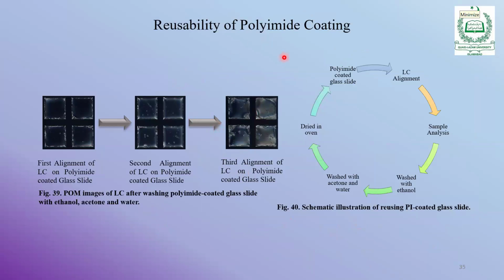Then there is the reusability of the polyimide coating. So first, alignment of liquid crystal on the polyimide coated glass slide, and the liquid crystal aligned. Then sample analysis was done. After the sample analysis, we washed this grid with ethanol and then with water and acetone. We dried the glass slide and used it again. So this is the second alignment. You see the dark image is the same as in the first one. It means the polyimide coating has not been changed or worn off.